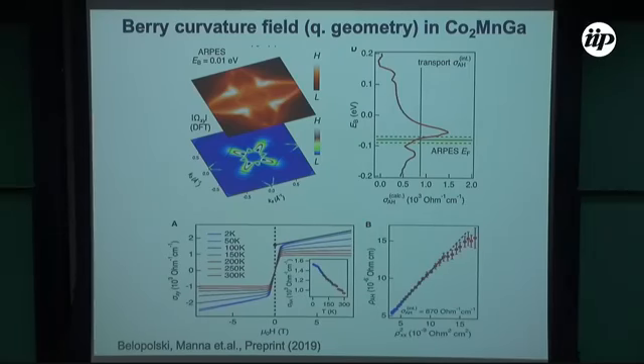In this particular case, the transport was carried out after we predicted the intrinsic anomalous Hall conductivity. When we extract the intrinsic anomalous Hall conductivity, it's 870 ohm inverse cm inverse, and it's pretty much in the right ballpark. It's a remarkable agreement.